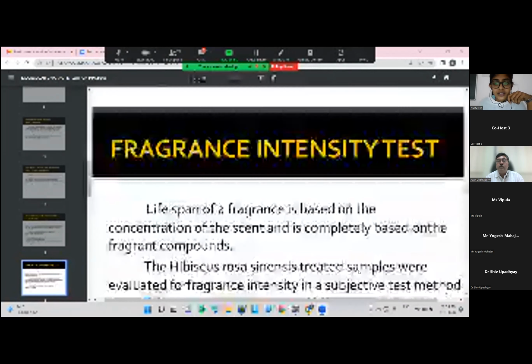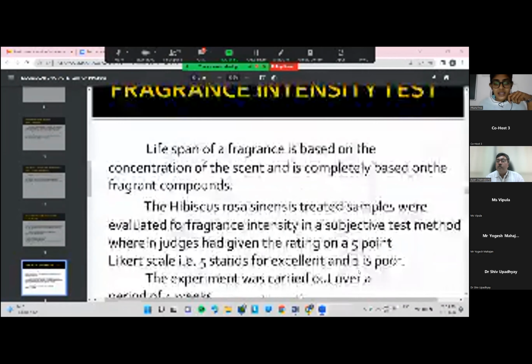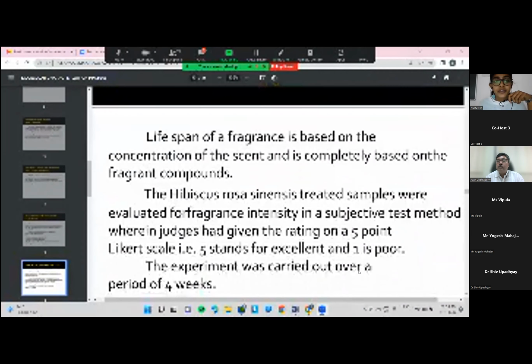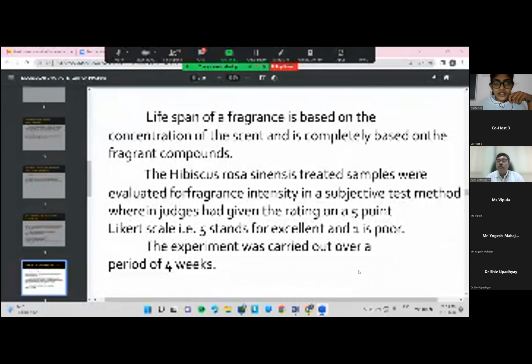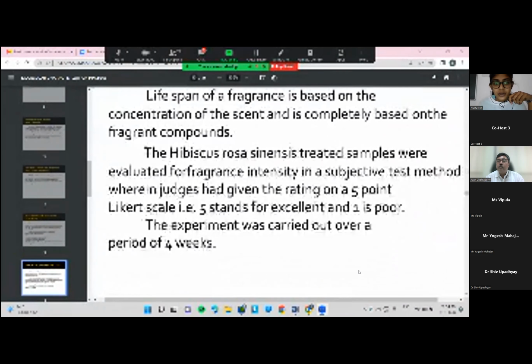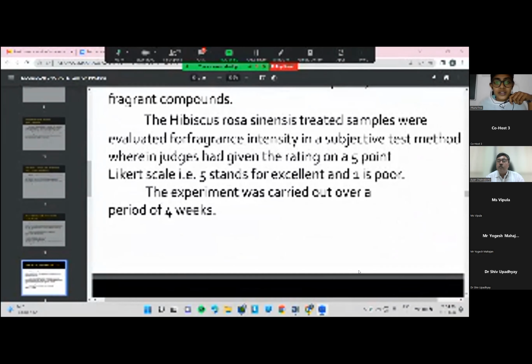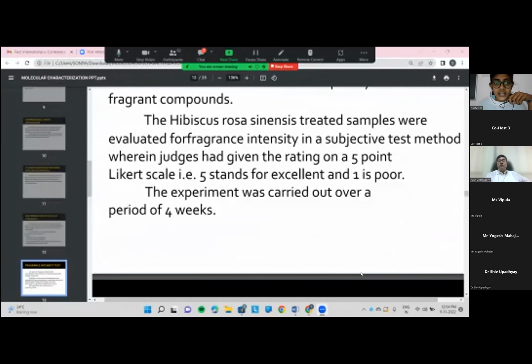Fragrance intensity test. The lifespan of a fragrance is based on the concentration of the scent and is completely based on the fragrant compounds. The Hibiscus rosa-sinensis treated samples were evaluated for fragrance intensity in a subjective test method wherein judges gave a rating on a 5-point Likert scale, where 5 stands for excellent and 1 is poor. The experiment was carried out over a period of 4 weeks.